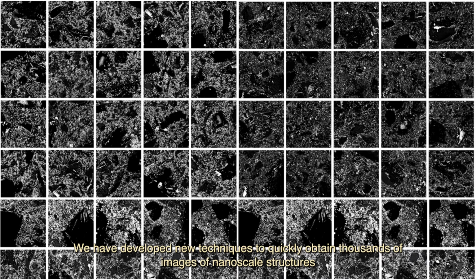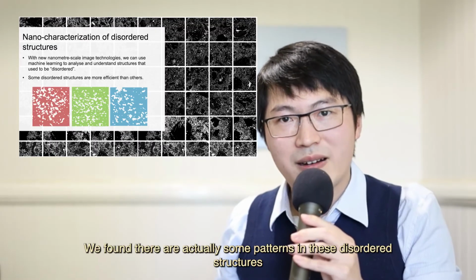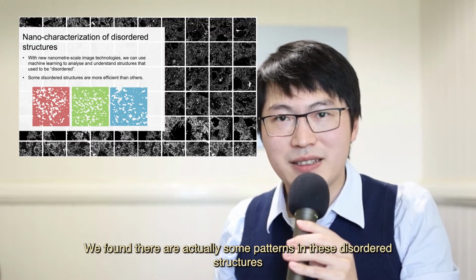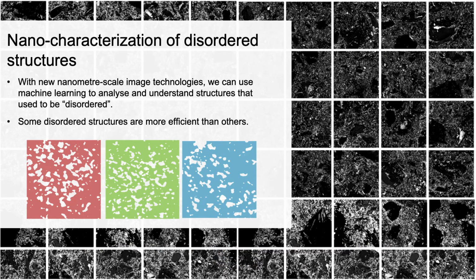We have developed new techniques to quickly obtain thousands of images of nanostructures, which allow the use of machine learning to analyze and understand these disordered structures. We find there are actually some patterns in these disordered structures, which makes some cement binder better than the others. These categorization techniques help us to improve the performance of these cements.